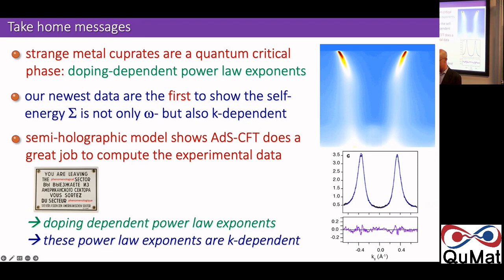It's optimally doped material. If you don't have a quasi-particle, your quasi-particle weight is 0, you don't have a Fermi surface. So then we start to have discussions about, we measure with photoemission from this point here, and we get some spectrum which looks like that. We measure from this point here, and we get some spectrum that looks like that. Depending on the doping level, we have other ones where the spectrum just looks like this from this point. So there it really looks like it's completely incoherent. And as a spectroscopist, we find it really hard. So how peaky does something have to be before we say it's a quasi-particle? I mean, the theory answer is clear. Its lifetime in energy units should be less than its energy. That's the Landau criterion, but that gives all real experiments a tiny bit of space around here where it may just work.